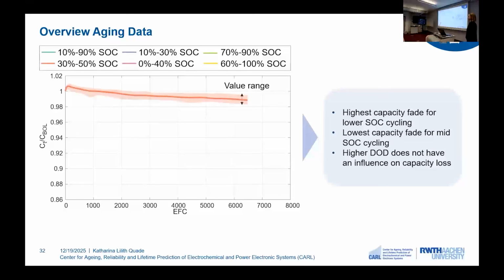First, we have the condition 30% to 50%. The shaded area corresponds to the value range because we have several cells within the condition. The thick line corresponds to the mean value. And I can now also include the condition 10% to 90% SOC. We can see we have a higher spread. However, the capacity fade is still very low.